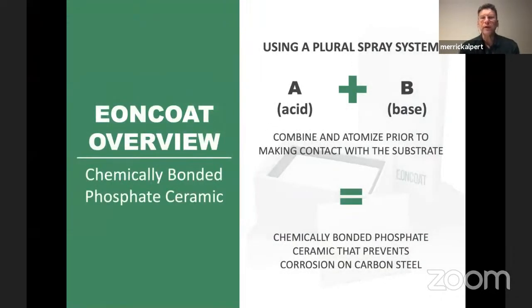To begin with, Eoncoat is a plural component system. You have an acid component and a base component. Those are both going to look like white paint when they're in the can. The acid component has roughly the same pH level as a glass of orange juice would, so it's not a very strong acid. The base component has roughly the same pH as an antacid tablet, so again, not a very strong base. But when you bring the A and the B together and you use them in a plural component pump and spray them onto the steel, you of course have an acid-base reaction, and that creates the chemically bonded phosphate ceramic that is Eoncoat.